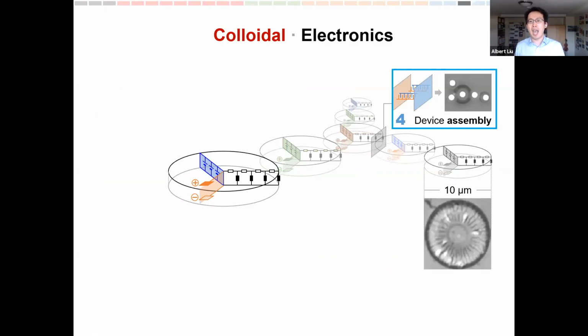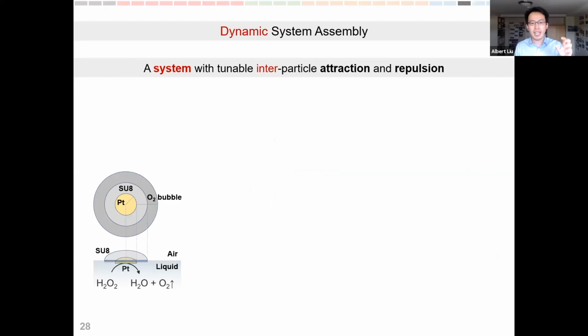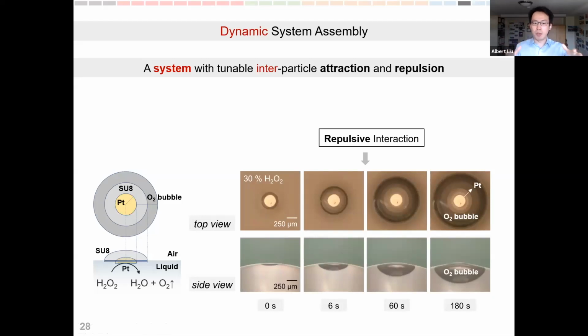And so I'll introduce to you how we can use the fact that we have this primitive way of locomotion to access systems-level behavior for dynamic device assembly. We take our little particle that has a platinum patch on one side of it, and then we turn the particle sideways, arrest it at the interface between air and the liquid phase, with the platinum facing downward, pointing at the hydrogen peroxide solution. Now we're still making a bubble because hydrogen peroxide gets decomposed into oxygen in the presence of platinum, but because the particle is sitting on top, it traps the bubble underneath, and the bubble becomes larger and larger, as you can see from these photographs. But it never really gets popped for a very simple reason: as the bubble grows larger, it blocks the platinum patch's access to more hydrogen peroxide. So this is a self-inhibiting reaction.